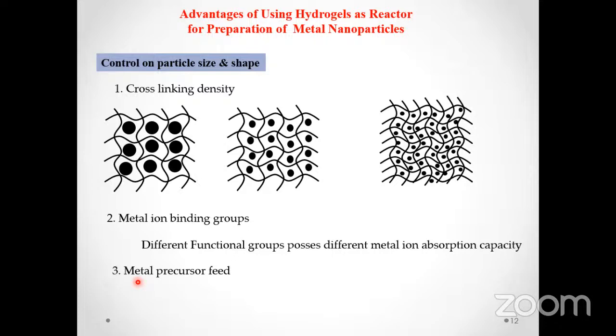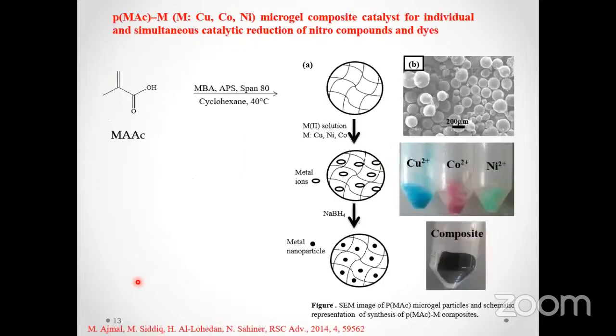Now, I will discuss a few research articles which I have published in this field, where hydrogels have been synthesized and used for the synthesis of metal nanoparticles. For example, here is the first one where we have prepared polymethacrylic acid hydrogels in the form of micron-sized microgel particles. This synthesis was carried out with the inverse suspension polymerization method at just 40 degrees centigrade. Once these hydrogels were prepared, it was observed that they had almost spherical morphology, and most of the particles had a size around 200 micrometers.